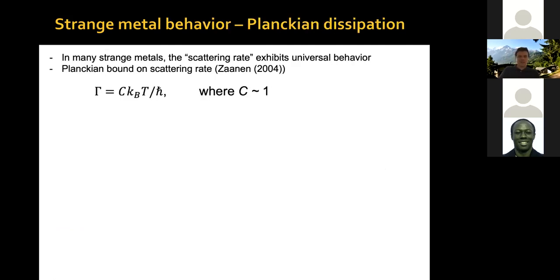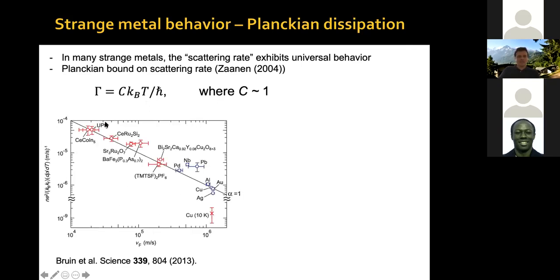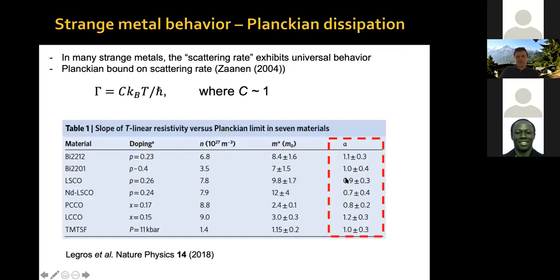Now, another thing that has been sort of a theme in recent studies of correlated materials is that the slope of this resistivity, when properly normalized, basically the scattering rate, seems to be proportional to temperature with fundamental constants and a prefactor which is of order 1. Okay, this was, I think, first studied systematically for a variety of materials by the Andy Mackenzie group. More recently, the group of Louis Taillefer has studied this. When the scattering rate satisfies this with a prefactor of order 1, people call this a Planckian bound on the scattering rate. This is a Planckian bound for C equals 1.